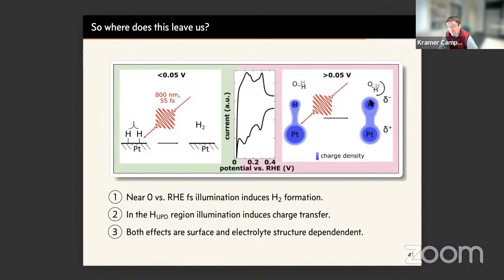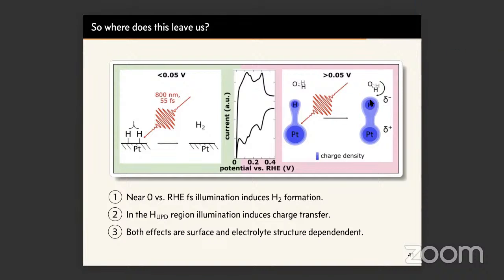I mean, this is of course true, right? In order for us to do this experiment, because we do optics, we are screwed if bubbles start to show up on the electrode. Then there's all sorts of scattering, and it becomes very difficult to know what the photons are that are reaching the interface and to detect the emitted field from the interface. So we try to operate in a situation in which H2 production occurs, but is sufficiently slow that bubbles are not generated. We also operate in a flow-through cell. This kind of accumulation to supersaturation and then bubble nucleation, either on the surface or homogeneous nucleation in solution, we don't want. Surely I do not mean that it's gas evolution. I mean that molecular hydrogen is in solution.